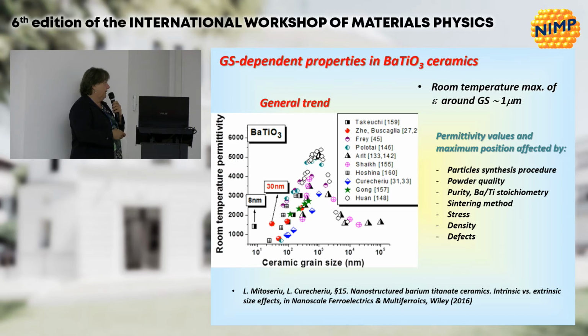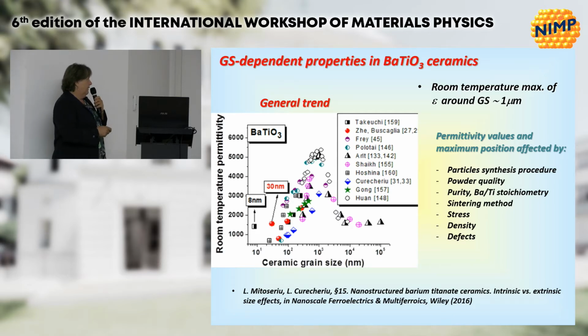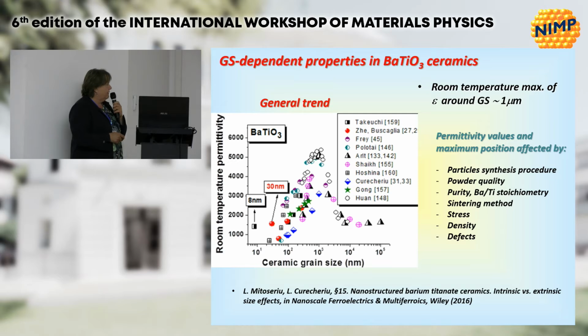The dielectric constant in barium titanate, according to a collection of data dated a few years ago that I collected for this chapter, and according to many other published reviews, shows a maximum around 1 micrometer. It shows a decay below this size, but also a decay for large grain sizes. These data show a very clear trend, irrespective of the source of powders, method of preparation, stoichiometry, stress, density, or defects.